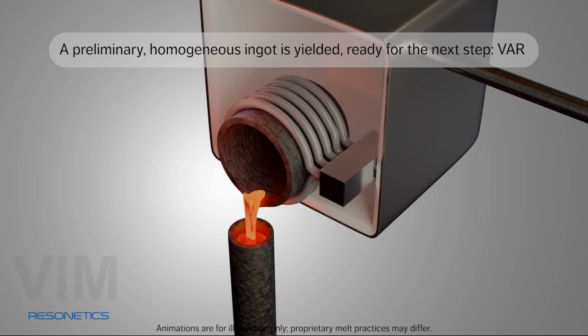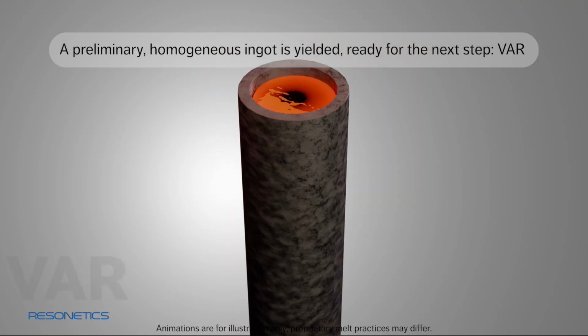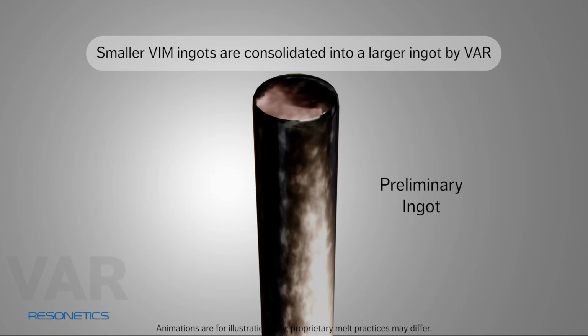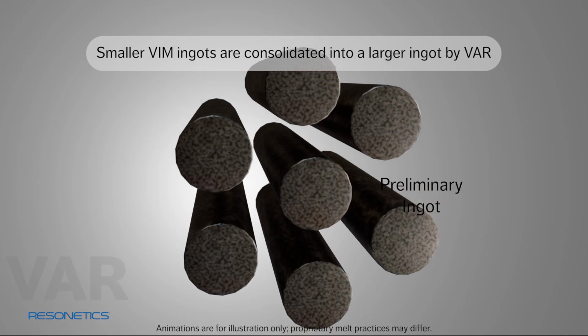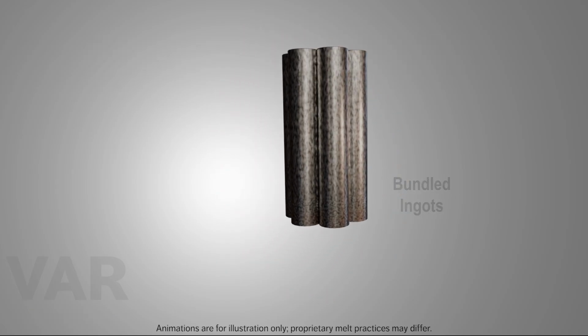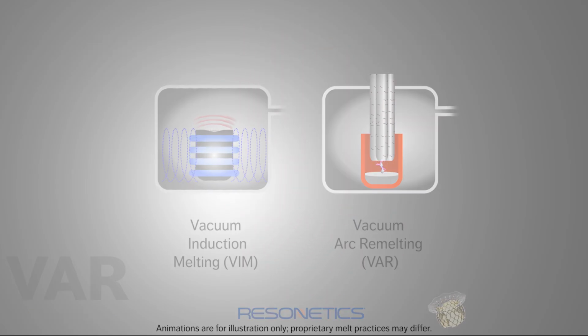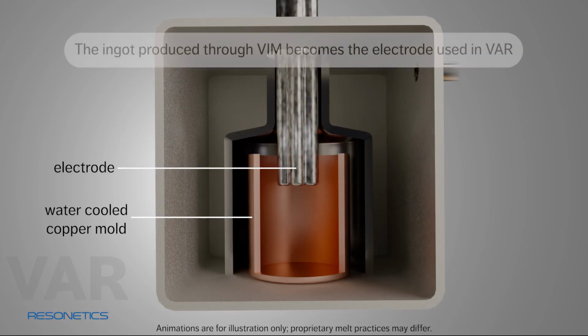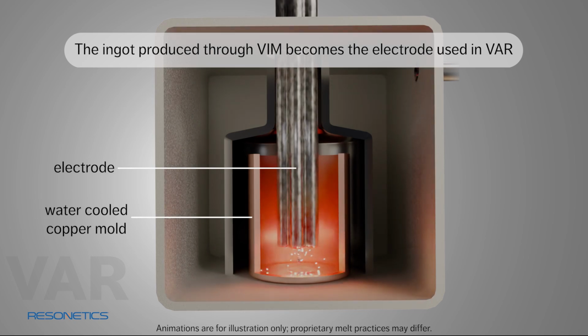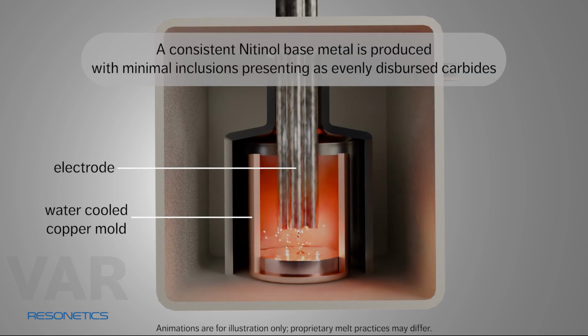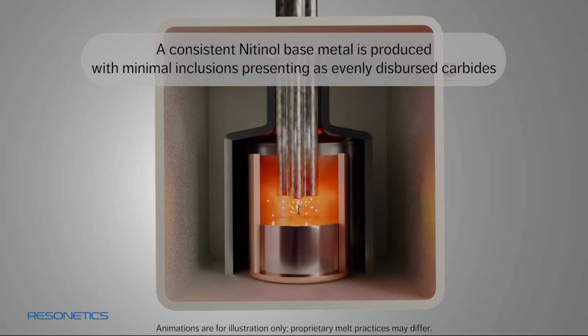In the VAR process, smaller VIM ingots are consolidated into a larger ingot by VAR. Essentially, the ingots produced through VIM become the electrode used in VAR, through which an electrical current is run, producing an arc that grounds to the bottom of the receiving crucible. Through this process, a consistent nitinol base metal is produced, primarily with small, evenly dispersed carbide inclusions.